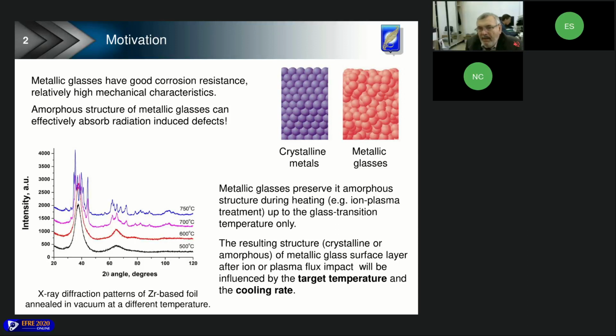For example, here you can see X-ray diffraction patterns of zirconium-based foil, and you can see that heating up to a temperature of 700 degrees resulted in crystallization of the foil. In general, interaction of ion and plasma fluxes with metallic glasses already leads to heating of the material surface layer. In case of pulsed intense ion beams and high temperature plasma flows, the temperature of the target surface layer could be much higher than the melting temperature.